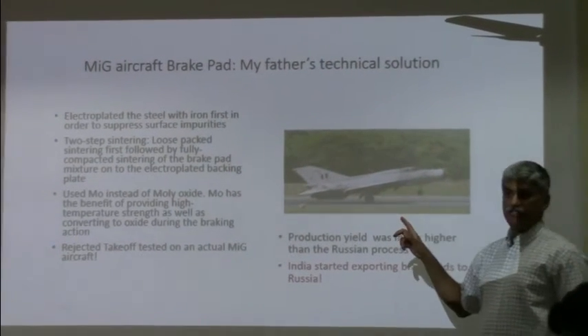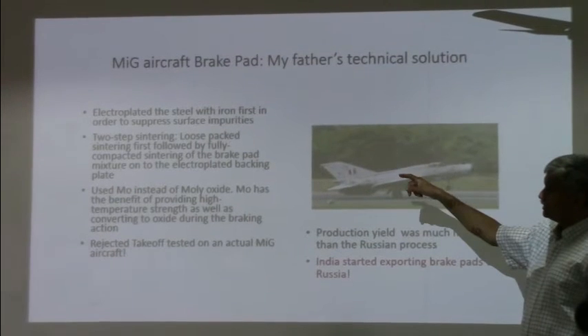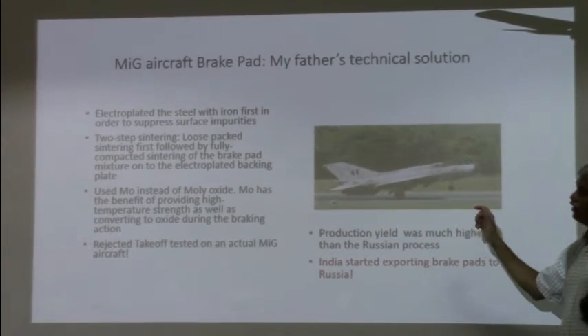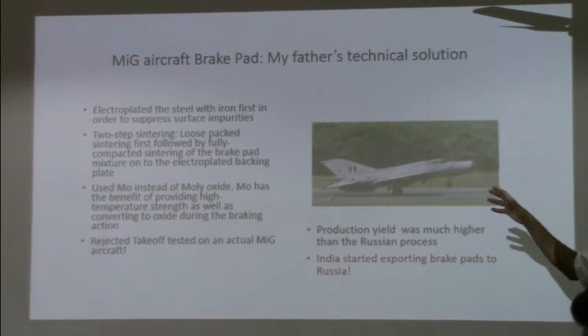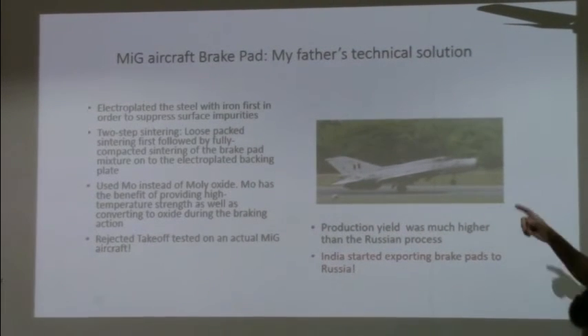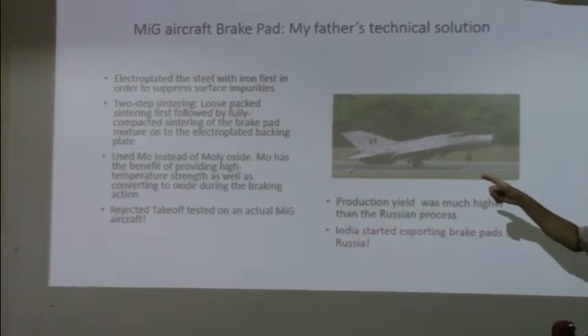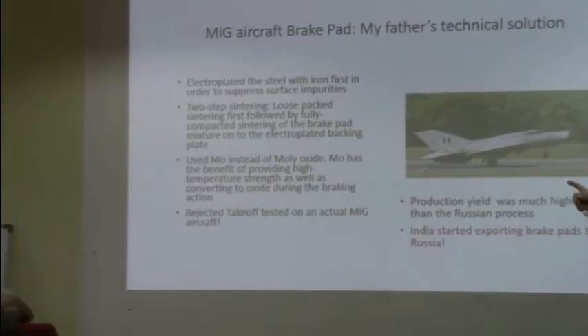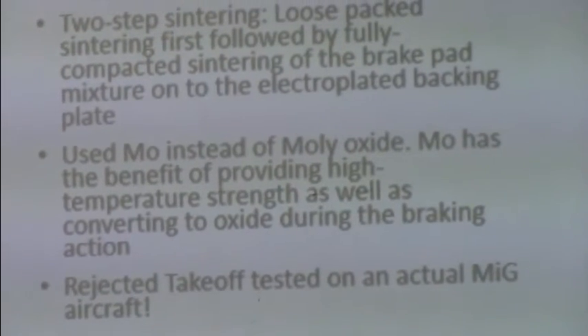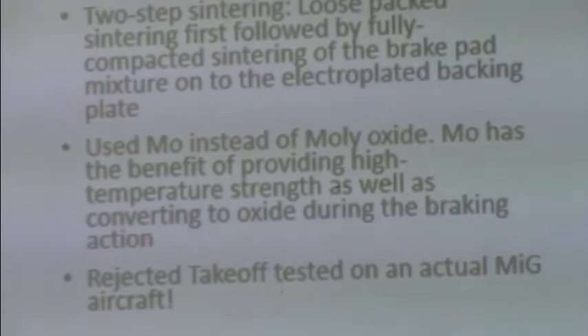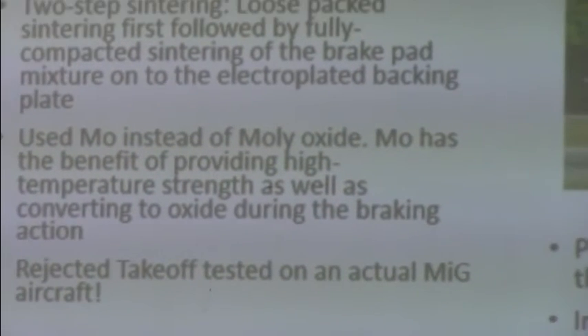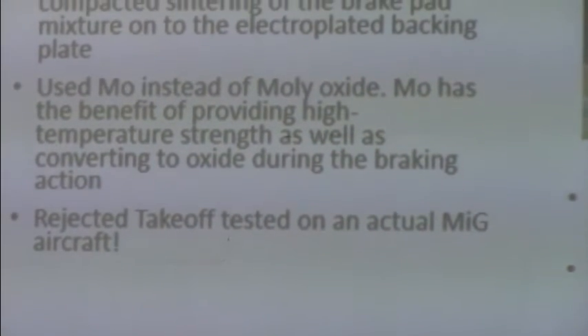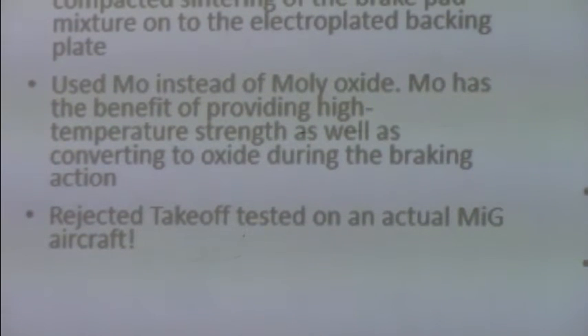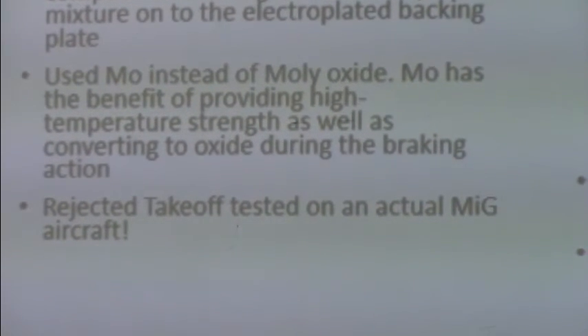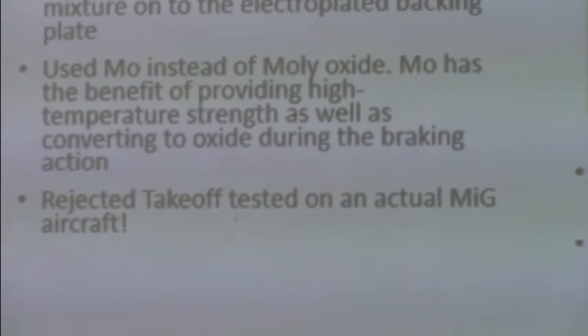And it was a two-step sintering process. So he did loose pack sintering first, followed by fully compacted sintering of the brake pad onto this electroplated backing plate. And unlike the Russians, he used molybdenum instead of molybdenum oxide. And the reason is that molybdenum has the benefit of providing high temperature strength to the brake pad, but during the braking action, it gets converted to oxide, so it does act as a lubricant also. So this did provide the end result which was needed without the molybdenum oxide.